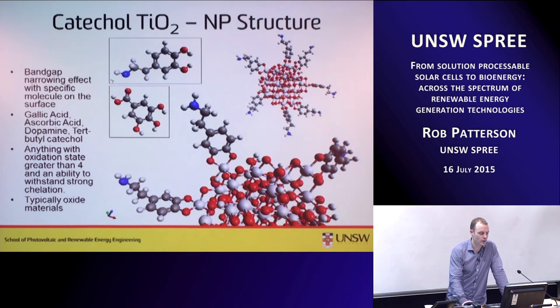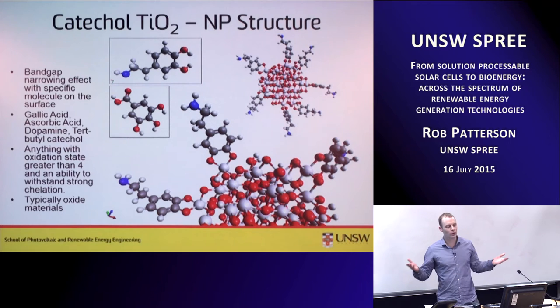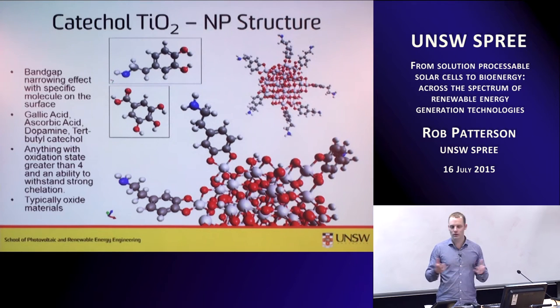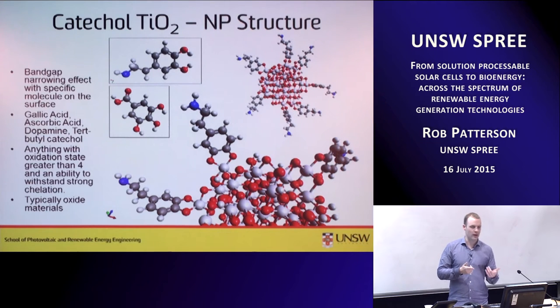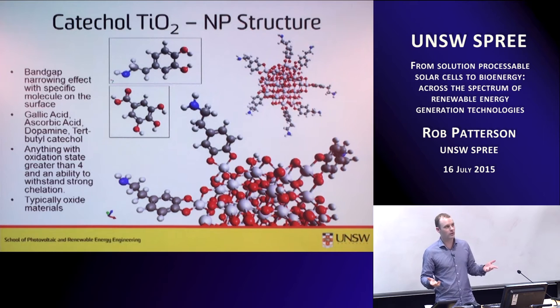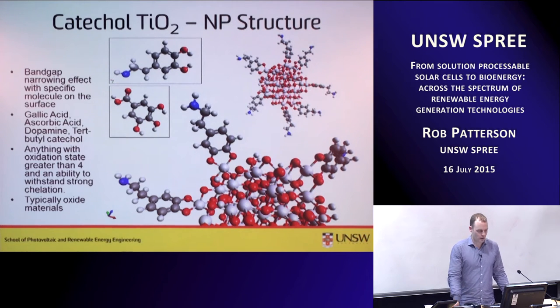And when this happens, we see a bandgap narrowing effect. All of the previous work in lead sulfide and lead selenide nanoparticles was about bandgap widening. You take a material, you make it small, and the bandgap gets wider. This is an opportunity to take a wide bandgap material and make the bandgap smaller. So if you're able to incorporate both of these effects, you might have a very tunable material.